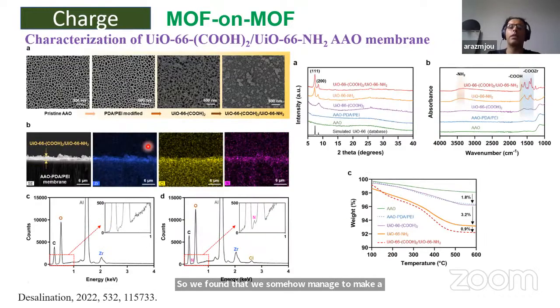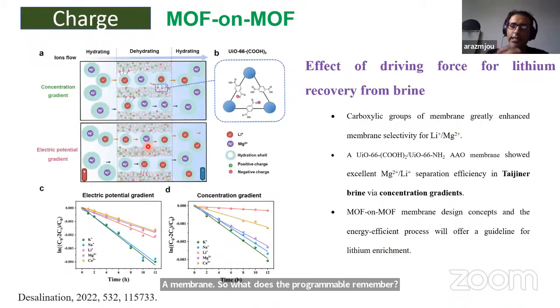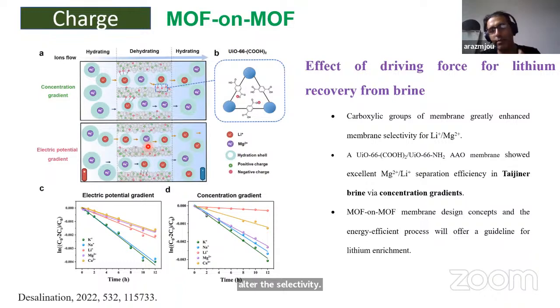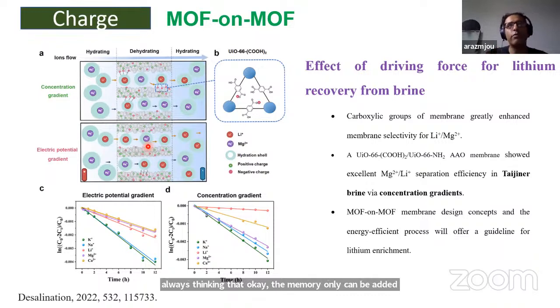What does the programmable membrane mean? It means that by conditioning the membrane to a specific cation, you can alter the selectivity. Let's say you have a brine with high magnesium or high sodium concentration. You condition your membrane by exposing it to a specific cation or anion, and that alters the selectivity. That was very interesting because before that, we always thought the membrane could only be adapted to a specific brine. Now we found a way to condition the membrane, making it suitable for a wide range of compositions.